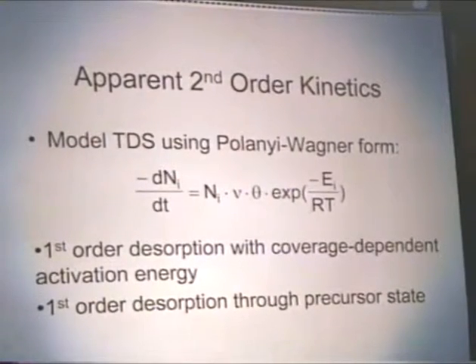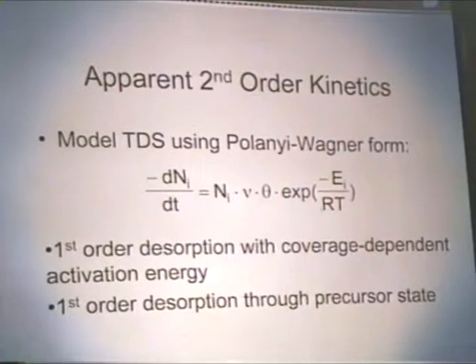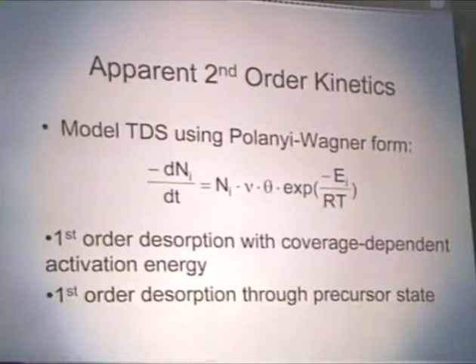People generally attribute apparent second order kinetics to one of two cases, and that is either first order desorption through a precursor state or first order desorption with coverage-dependent activation energy. We decided to model these two cases, and we did this using a Polanyi-Wagner rate expression. n_i is the concentration of species i on the surface, ν is the pre-exponential factor, and θ is the coverage. And for the first case of coverage-dependent activation energy, we simply plugged in an equation to model the coverage dependency of the activation energy, and then used that equation to model thermal desorption.